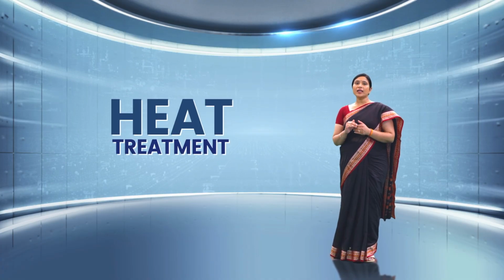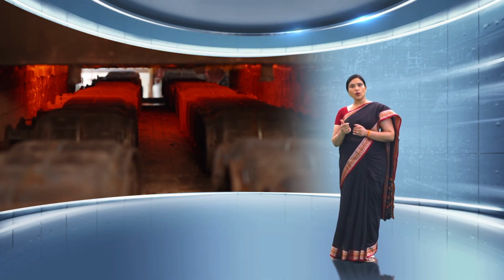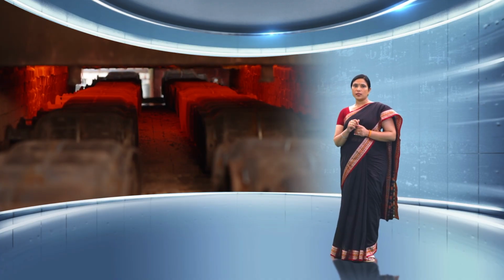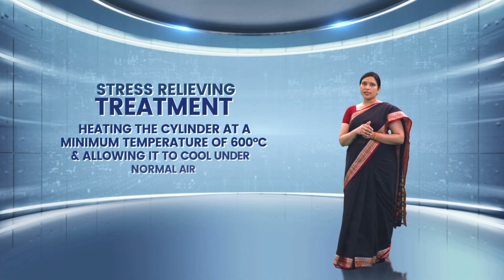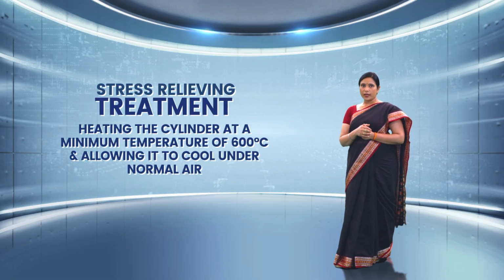Following welding, we have the heat treatment stage. This involves heating the cylinder to a specific temperature, allowing it to soak and then carefully controlling the cooling process. This process is vital for relieving the stress accumulated during welding, ensuring the cylinder's integrity. During welding, the metal is heated to its melting point. During cooling, after the welding process is completed, the rate of cooling is different at different points, which induces stresses in the material. The stress relieving treatment involves heating the cylinder at a minimum temperature of 600 degrees Celsius and allowing it to cool under normal air. The cooling rate is uniform throughout the cylinder and hence the stresses are relieved during the heat treatment.